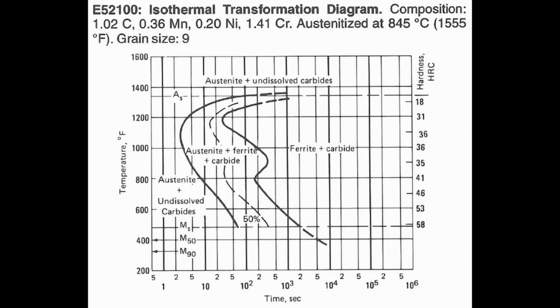Another important part of the diagram is MS. You'll see MS here on the diagram. That means martensite start. That's where you start to get martensite formation. So typically when you talk about austempering for bainite, martensite start would be your minimum temperature, because below that point you're starting to form martensite. So to form bainite, you'd have to be above martensite start to ensure it's all bainite and no martensite.